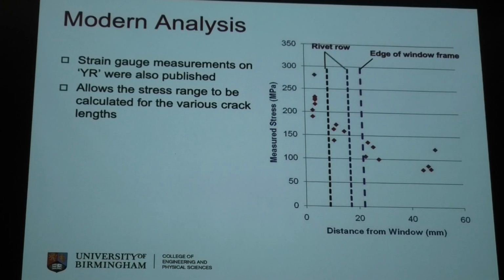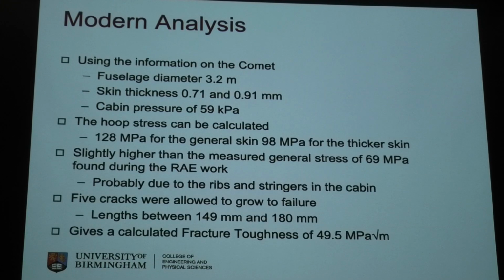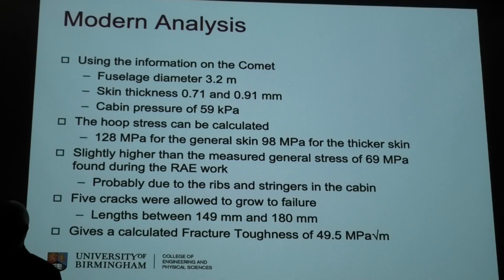although it's a bit difficult to find these days, and we can map it to these, we can look at the strain gauges, and we can start to take the data from the Comet, and we can say fuselage diameter, and this is where I switch to modern units, but you can see the units up there. We can take the data from the Comet, the skin thickness, the stresses, we can plug it all in. We can calculate the hoop stress generated by the cabin pressure loads. We can say there's probably ribs and stringers in there, which will modify it slightly, and we can do certain approximations. And we come out with a stress that's generally higher than the RAE work, but not horrendously so. And that's assuming that the ribs and stringers then take that back down again.